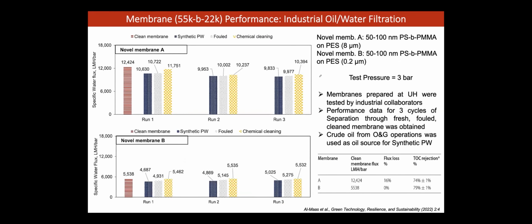But we worked with ConocoPhillips, as I said, and it is published. We actually ran several real liquids, like dirty water, whatever comes out, called process water, PW, crude oil in all its different forms. Then they run it through some chemical cleaning treatment and retest it three times. Our glycopolymer membranes actually stood through this whole process really well. And you can see that we had 74 to 79% rejection rate of TOC. TOC is total organic content. So it worked really well, very close to commercial membrane. They were very excited, and this is, of course, work with Qatar University. So they have real potential.